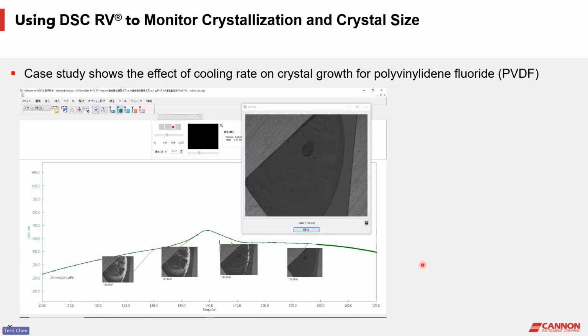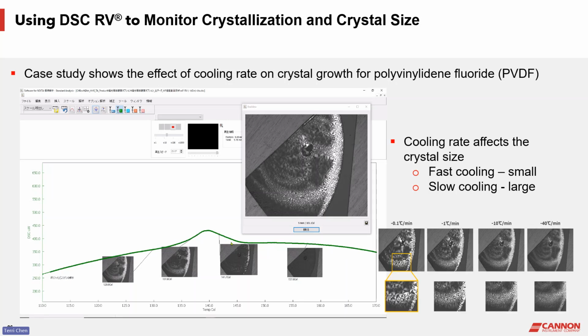As we're cooling the polymer, when the temperature is approaching 140 degrees C, which is the crystallization temperature of PVDF, we start to observe the formation of the crystals. Also, using this camera view, we can study the influence of cooling rate on the size of the crystals. From our measurement results, we can clearly see that decreasing the cooling rate lets the crystal structure form better, and the size of the crystals is much bigger compared to using a faster cooling rate.